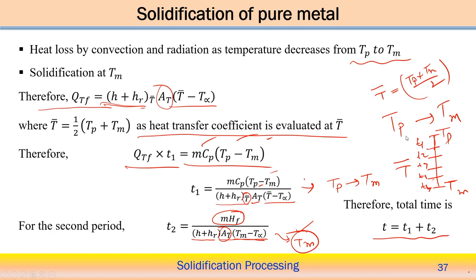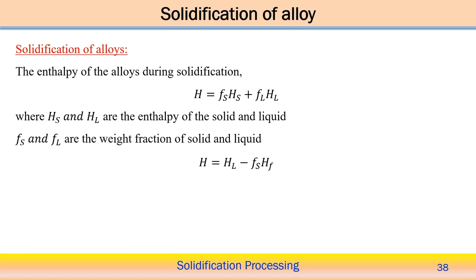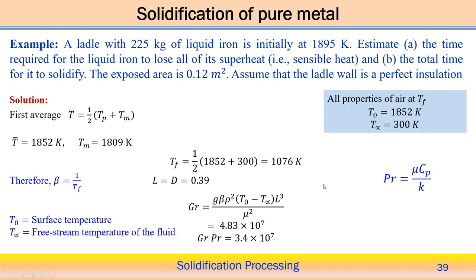So this is one approach, which we are considering just to estimate the values of the heat transfer coefficient at a particular temperature. Now if we consider the solidification of an alloy, the enthalpy of the alloy during solidification is basically H equals FS HS plus FL HL, where HS and HL are the enthalpy of the solid and liquid, and FS and FL are the weight fractions of the solid and the liquid phase. So enthalpy should be considered when you are considering the solidification of an alloy system.